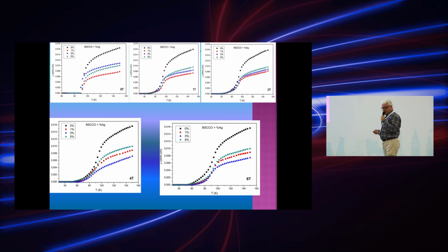Now, these are the new results. We measured them and analyzed them 2 months ago, and now we are still calculating some parameters. This is the magnetoresistivity of our samples, in order to see the flux creep model and their behavior in magnetic field. As you see, at 0T the resistivity is dropping and decreasing. By increasing the applied magnetic field, the TC offset is shifting towards lower temperature. This is the general behavior of bismuth 2212 samples, high TC bismuth samples.